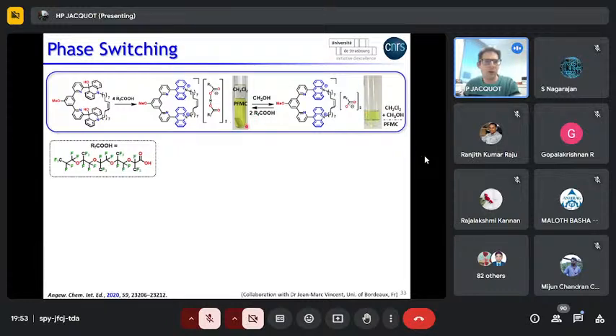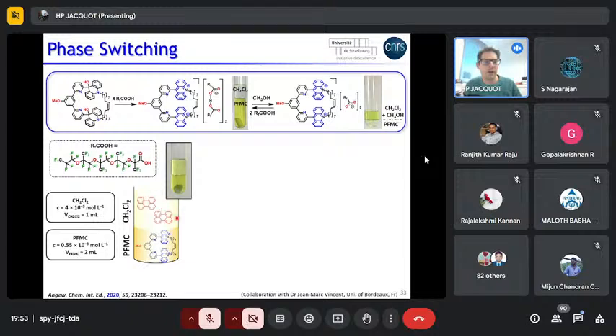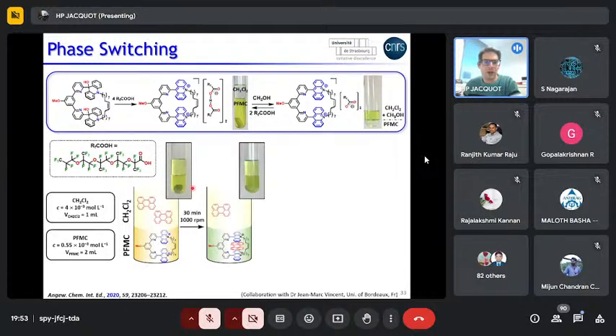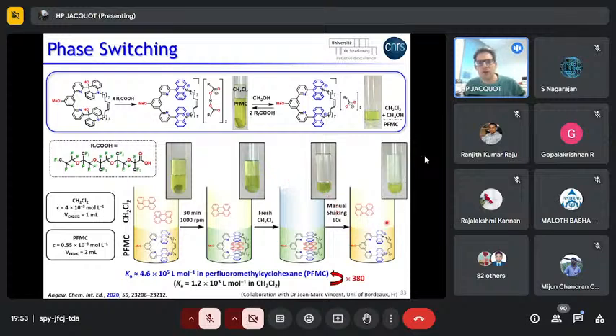Then also we wanted to exploit our enriched fluorous phase with the macrocycle for the extraction of perylene from DCM. So this is what we did. After stirring, we have a color change from yellow to green. So this means that you have the formation of a host-guest complex. And then upon changing DCM by fresh DCM, you can release the captured guest. And this experiment, thanks to a few control experiments, allowed us to estimate a binding constant in the PFC phase, which is 2 orders of magnitude higher than it is in DCM. So basically, Jean-Marc was right. Perfluorocarbons can boost the association between a host and a guest due to their solvophobicity.